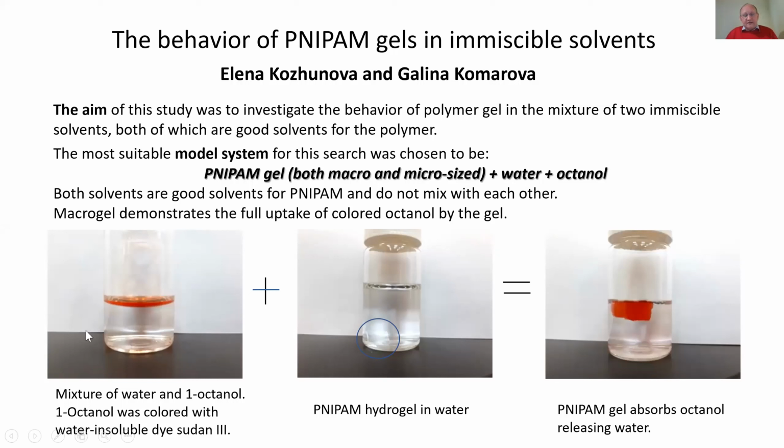Here in the left picture, we have just two immiscible liquids, so phase separation of oil and water. In the second picture, we have a microgel which swells in pure water. But if we take this microgel and put it into this two-phase liquid, what we observe is complete release of water from the microgel and full absorption of the oil.